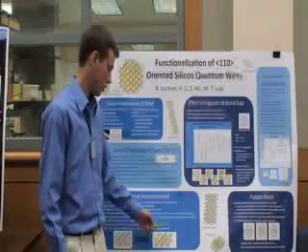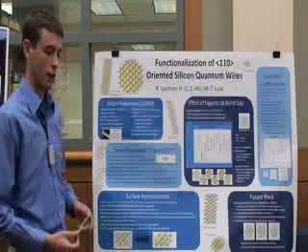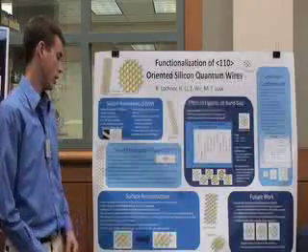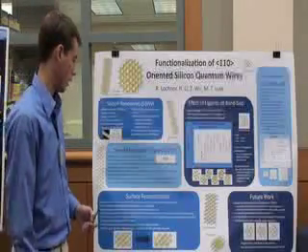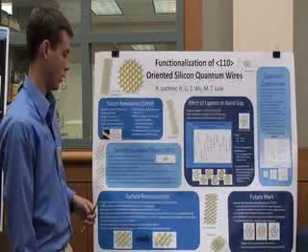Then it reconstructs to leave only a single hydrogen or ligand and forms a dimer of silicon, and that's interesting. The resulting structure is about 0.5 eV lower in energy per unit cell, and that was also a known result for some wires, but we showed it with the 1.2 nanometer and 1.6 nanometer wires also.